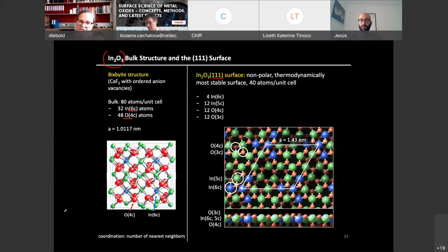The main thing is that on the surface, you have a really large number of atoms. You have 40 atoms just in the unit cell on the surface. You have 4 indium atoms that are 6-fold coordinated, 12 that are 5-fold coordinated. And what will be very important later on, we have 12 oxygen atoms that are all surface atoms, and many of them have a slightly different coordination. As we'll show you in the end, hopefully today or maybe tomorrow, all these oxygen atoms here that are 3-fold coordinated have a slightly different surface chemistry.